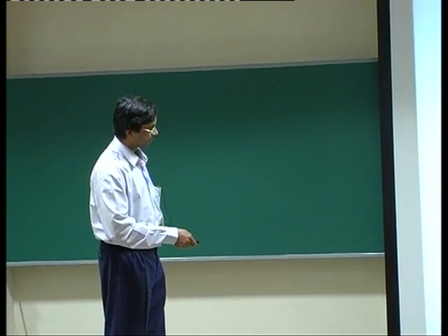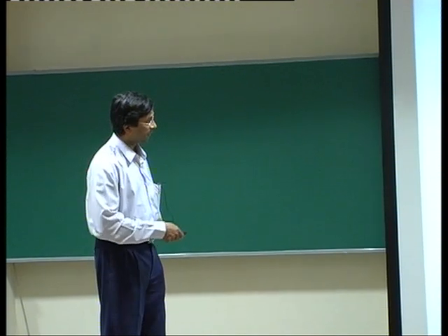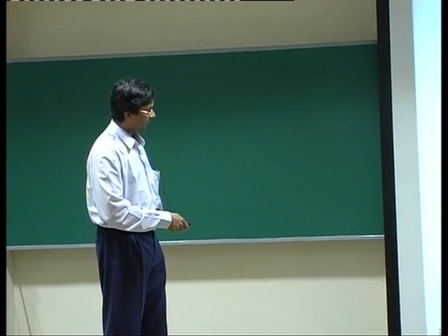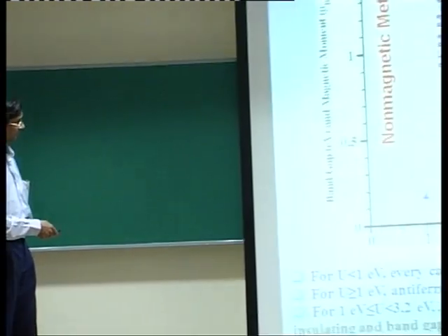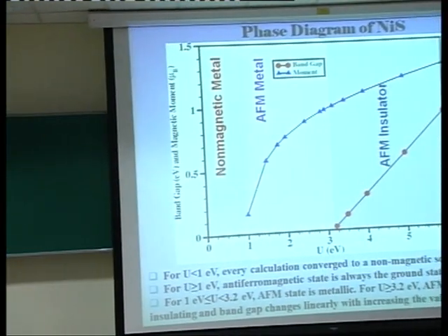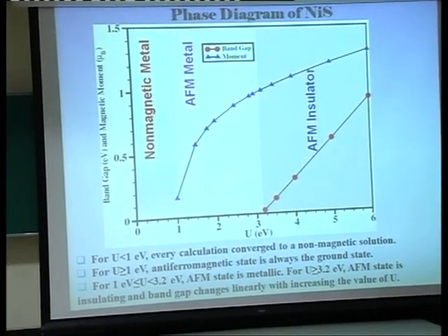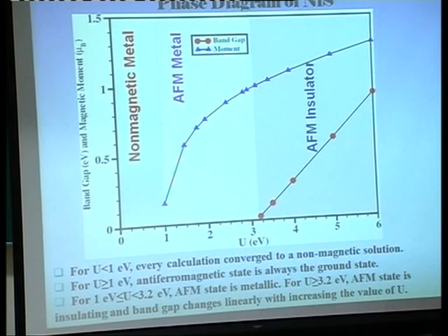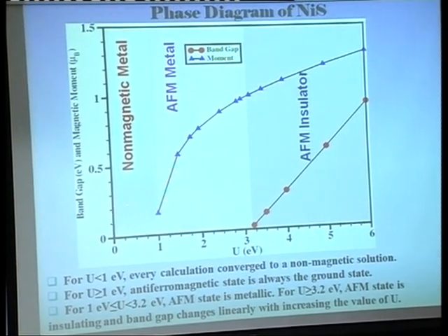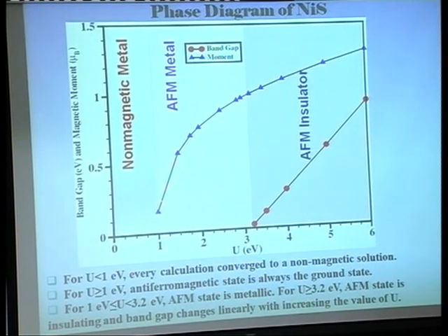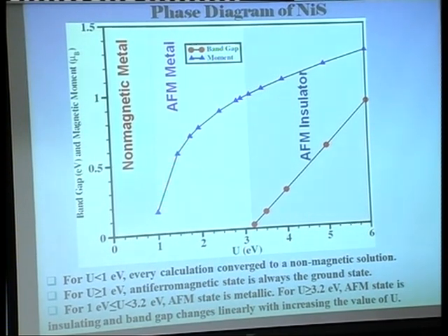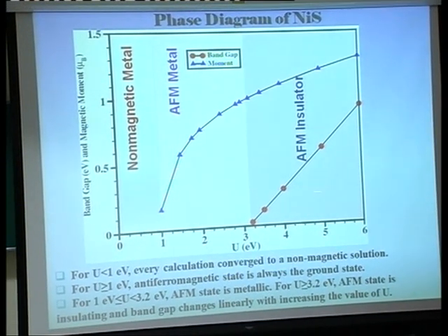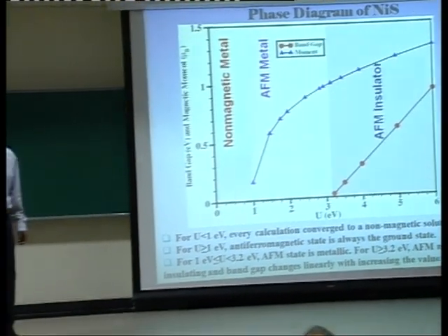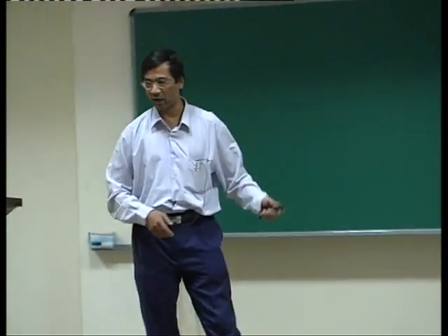Everything on that side must be insulating, everything on this side must be metal. And there's a magnetic moment, and that implies that everything on that side is magnetic, everything on this side is non-magnetic. And the magnetism that's lowest energy in our case is an antiferromagnetic metal. Antiferromagnet. So immediately you can see that what I have is a non-magnetic metallic slice here, then an antiferromagnetic metallic slice here, and then an antiferromagnetic insulating slice beyond. So these are the three segments that come about, and let's look at the electronic structure of each of these types.